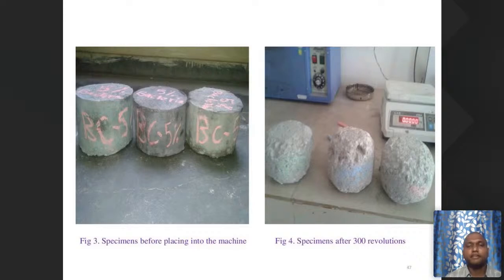Yeah, these are the specimens we casted. 3 specimens each for the river sand mixes and also crushed stone sand mixes. Those are BC5, BC10, and BC15, that is 5%, 10%, and 15% of bacterial solution by weight of cement. At every 50 revolutions, we take the specimens out and clean them, and we note down the value. Again we put them in the machine, switch on the equipment, and run at 32 revolutions per minute. After 50 revolutions, again we take out and remove whatever debris is inside, and put them back. We do the same process up to 300 revolutions.